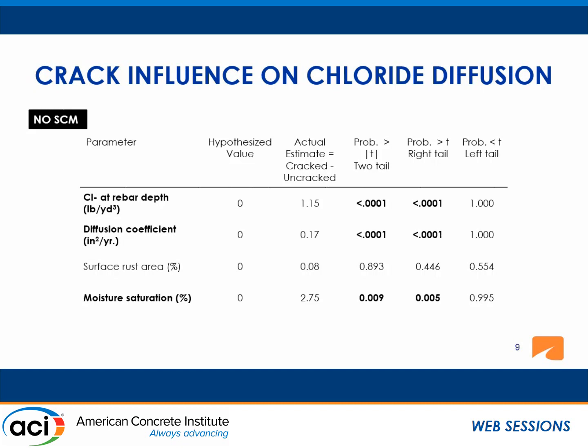And the bold factors, the chloride at rebar depth, the diffusion coefficients, which is the rate of diffusion, and the moisture saturation were significantly higher at the cracked locations compared to the uncracked locations from this analysis. And these were all for the decks with no SCM.